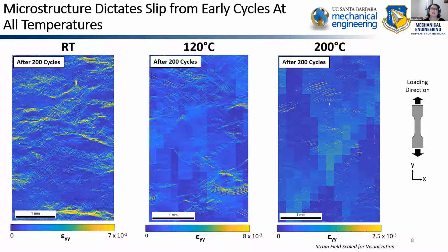So the idea is that it's more homogeneous. The material itself has less anisotropy. And I understand, but I would expect more homogeneous, but then also a higher strain if you believe that the yield stress drops, which makes sense at a higher temperature. Yes, and everything. But the strain doesn't increase; it actually decreases, right?